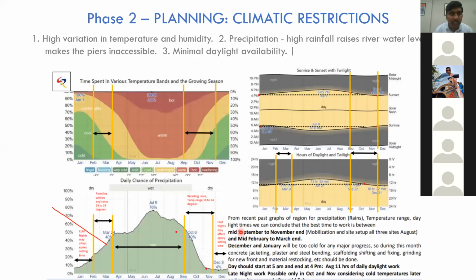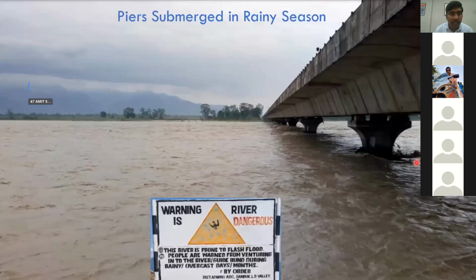And we had to see, basically, site execution is more difficult than how we assume. In this particular site, the daylight hours are very limited. The temperature is low. Based on the amount of rainfall in the rainy season, you need to plan your retrofitting activity, because once it starts raining, the height of water in the river will be quite high, and you would not be able to do any retrofitting on the pier because it will be submerged. So all this gave us ultimately a 2 months window in a year. Okay, so we could only do the retrofitting work for 2 months in a year for this particular project. So that was the planning. I told you, right, the piers will get submerged. So you cannot do FRP wrapping on a submerged pier, right? So this is what it is.